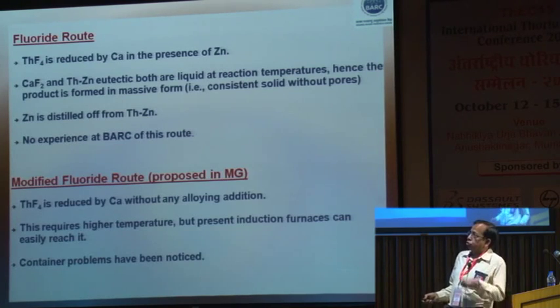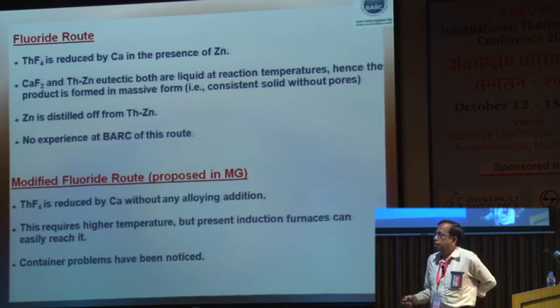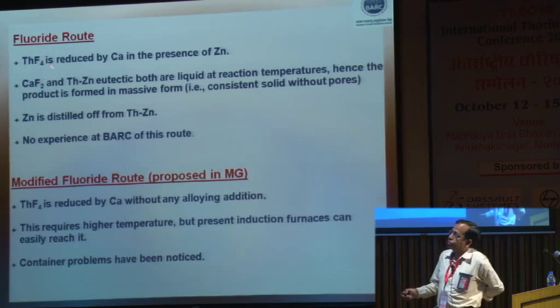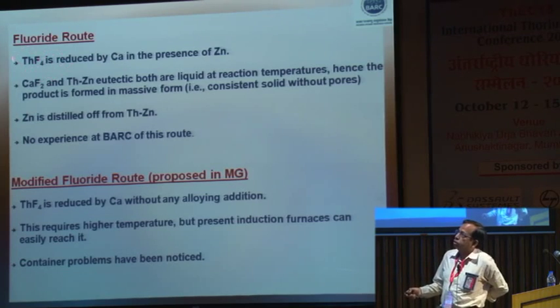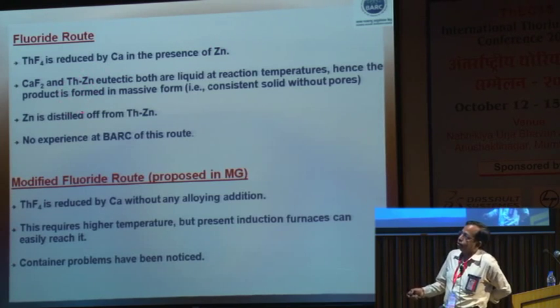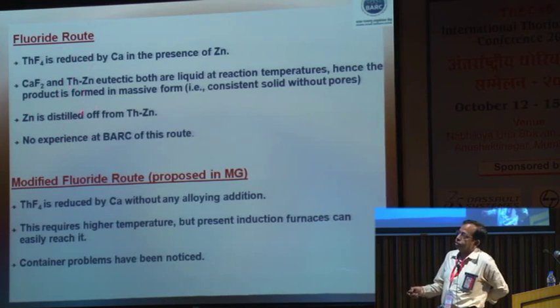The international route is through the fluoride route, where you reduce thorium fluoride with calcium in the presence of zinc. The presence of zinc means that you get the product in the form of a eutectic of thorium and zinc, which has a much lower temperature, and if you heat that, you can remove zinc and get good quality thorium. We have not started on this.